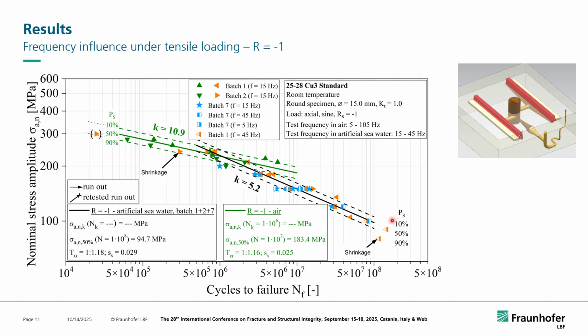We also made some tests beyond 10 to the power 8 cycles, two or three. We could not see a knee point. That's what we hope to see, something like a flattening of the curve here. But this is so time consuming and really a lot of work to get to those results under 15 Hertz. So we had to stop there occasionally.